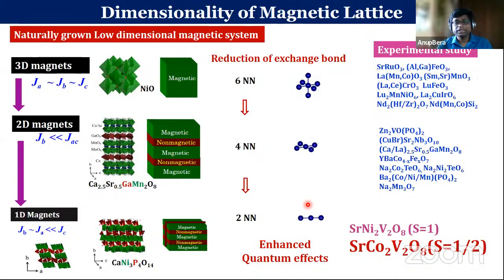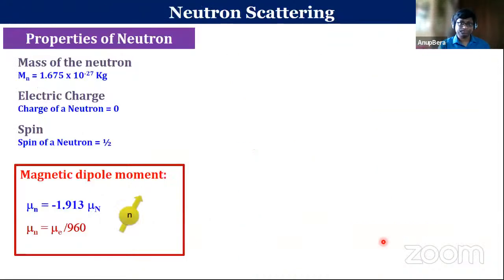But today I will show the results from the last compound, which is strontium cobalt vanadium oxide, which has a spin half. It is not really spin half, but an effective spin half, as Professor Yusuf explained for the other compound. Due to the spin-orbit coupling, the effective spin becomes half here. And I'll quickly compare the result with the spin-one counterpart, which is based on nickel, and I'll show the experimental proof of Professor Haldane's theory.